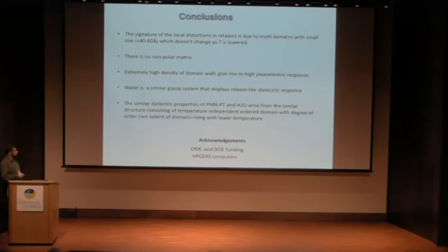This high density of domain walls gives rise to piezoelectric response, and extremely high piezoelectric response. And again, we see that these are two similar glassy systems, water and relaxers. And I believe that this is not a general feature, but it comes from the same structure of these local fixed size correlated polarization nanodomains, which do not get bigger as you lower the temperature, but just get more correlated. And I'd like to acknowledge funding sources, and thank you for listening.